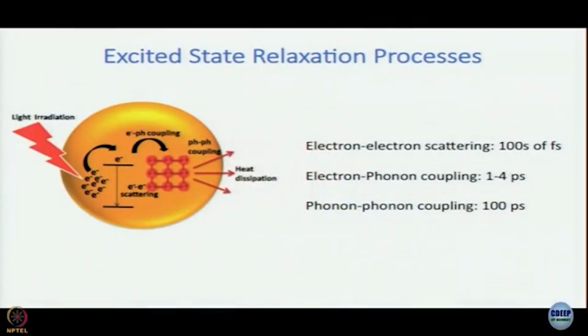All right. So, now this electron scattering is the fastest, and we will show you some data later. That takes place in hundreds of femtosecond, really fast. Then you have electron phonon coupling that takes place typically in 1 to 4 picosecond, and phonon-phonon coupling is the slowest step that takes place in 100 picosecond.